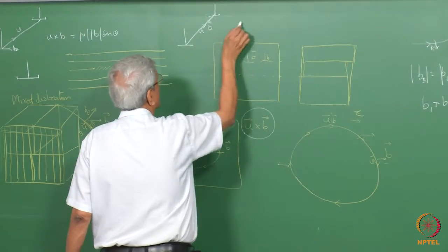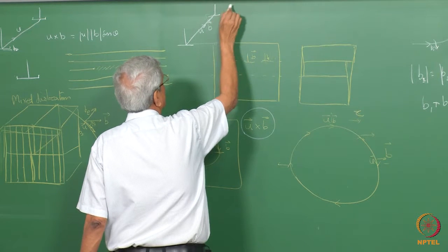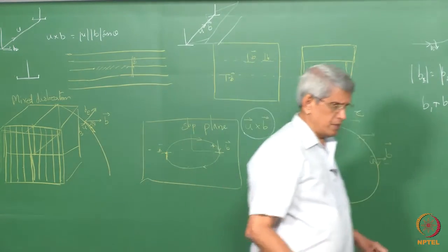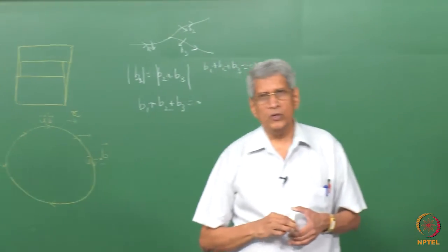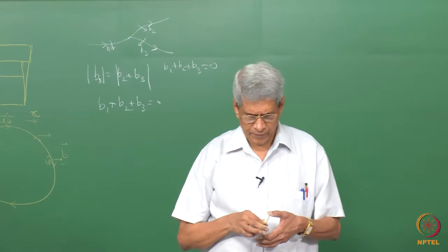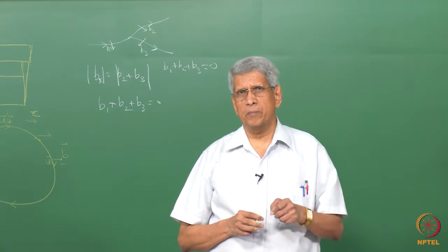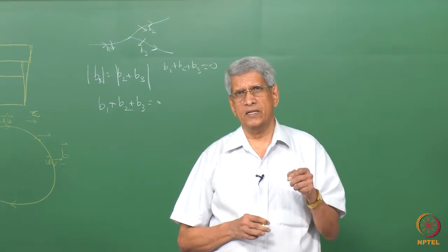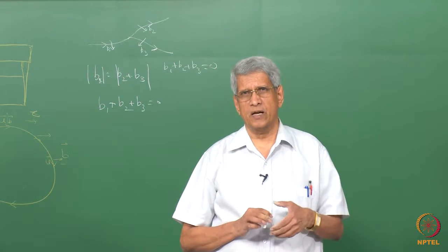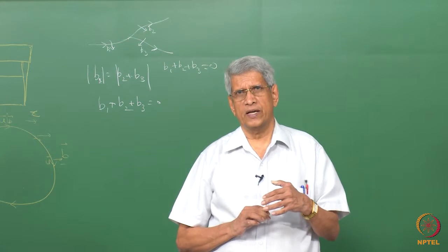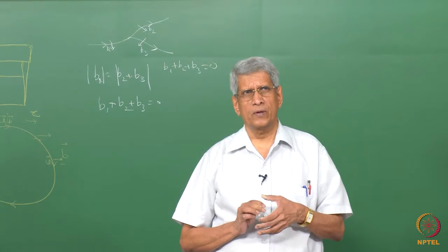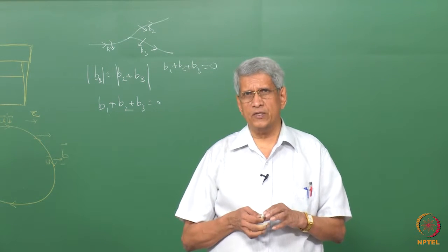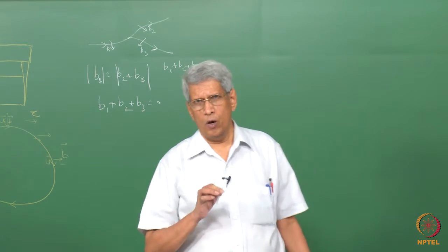Maybe this is one plane and there is going to be another plane which may be inclined with respect to it. These two planes in which the same dislocation can move, depending upon the direction in which the external stress is applied. Take the component of that in the slip direction, slip plane. Whichever one has got the higher maximum resolved shear stress, that is the plane in which the dislocation will move.